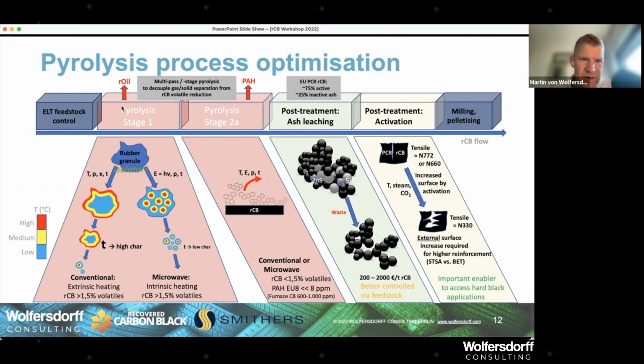Second stage in the pyrolysis, here in the pyrolysis process, stage one really is to get rid of all the rubber polymer, to put the whole rubber polymer in gas phase. The stage two is to evaporate all the remaining rubber from the surface of the recovered carbon black. And this is a sketch where I tried to show. These are all polycyclic aromatic hydrocarbons. You can see those rings. So it's very, very important to have a low PAH content. We'll get to that as well in a moment.